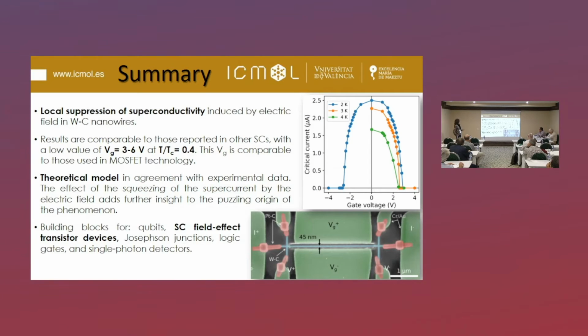So, a summary of this first part of my talk: we obtain a local suppression of superconductivity induced by an electric field, we obtain this superconductivity modulation at really low values of the gate voltage, and this gate voltage is comparable with those used in MOSFET technology, and we developed a simple theoretical model in agreement with the experimental data. And of course, these kinds of devices could serve as building blocks for cryogenic superconducting field effect transistor devices, Josephson junctions, logic gates, and single photon detectors.